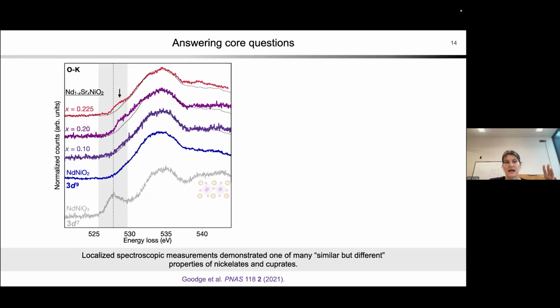And what we're doing here is we're slightly changing the electronic dopings or the carrier concentration in these materials. So what we do is we substitute some of the neodymium, in this case for strontium, which slightly changes the average nickel valence. And so you kind of, instead of a d9 in the blue case, you might have like a d8.8 in the sort of purple case, right?